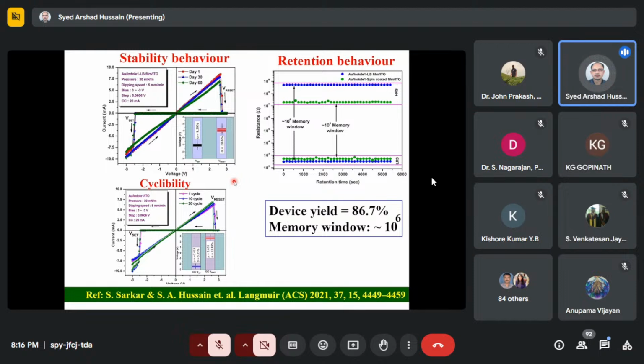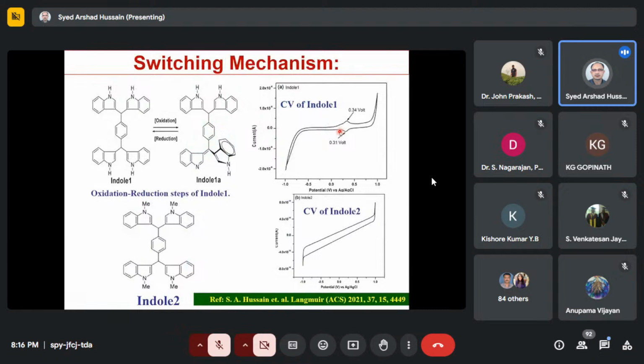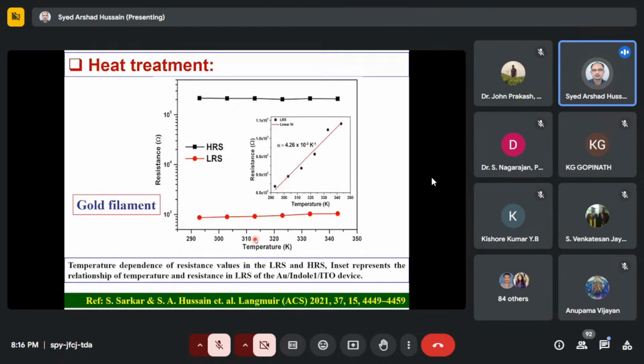Then we optimized different conditions. We optimized the device yield. It's 86%. The memory window is very high, 10 to the power 6. We studied the retention also. Okay. And we analyzed the mechanism also. So we are not going into details here, but we have seen that oxidation and reduction play an important role in changing the state from high resistance to low resistance, then again reset from low resistance to high resistance state. We studied the device behavior by changing the temperature also and measured the temperature coefficient, and we found that a gold filament formed between the two electrodes. Okay.